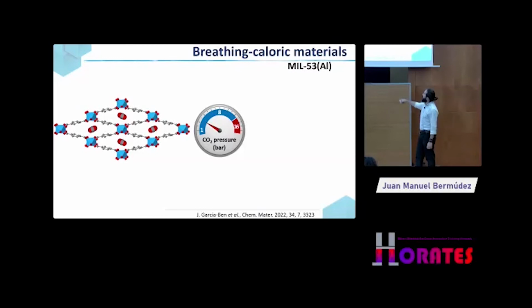Which is a family known as MIL materials, metal organic frameworks that are denominated MIL, which have a very interesting transition, which is known as breathing transition. So this kind of materials, when you pressurize them, well, I don't know if you have heard about metal organic frameworks, but they are materials that are very porous. So they are normally used to absorb and separate selectively gases. So the hybrid perovskites are very dense materials, so they cannot absorb gases. Metal organic frameworks have very open pores, so you can allocate gases in there. Okay, they can be used to absorb gases.